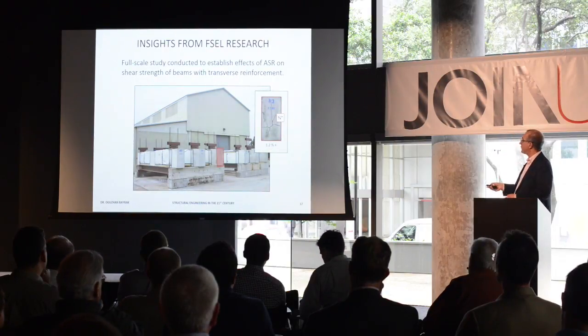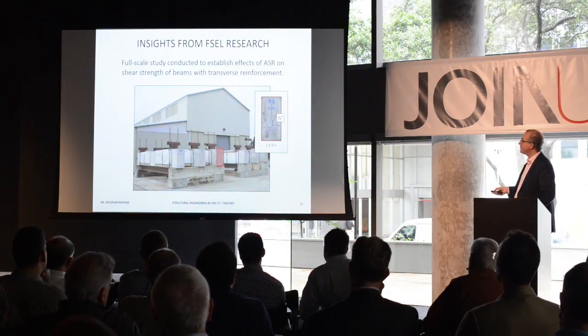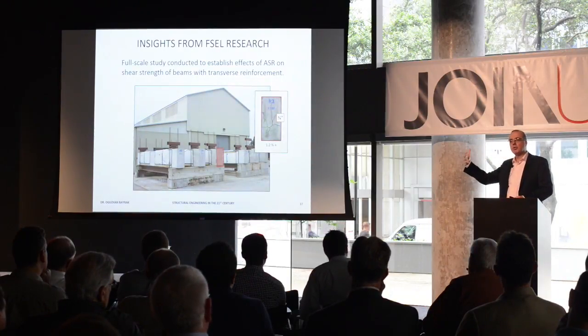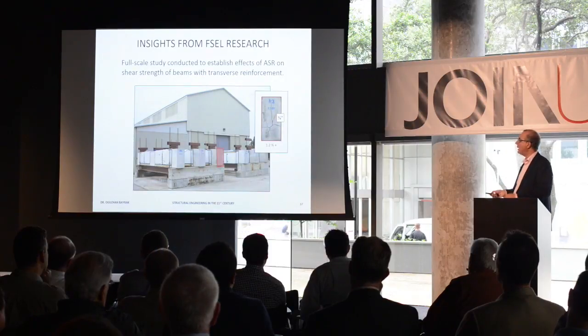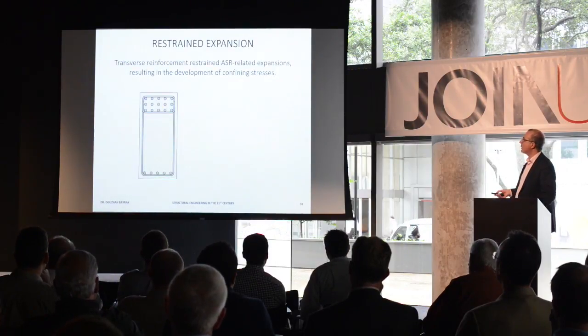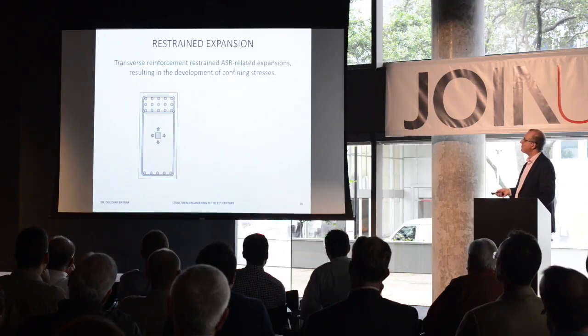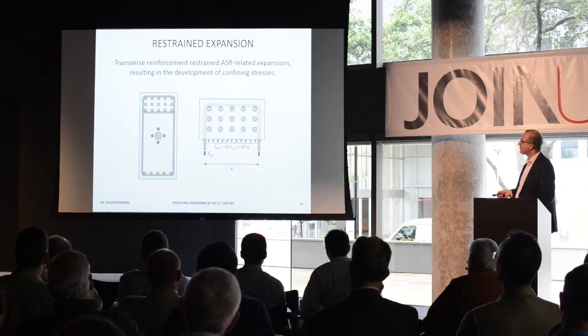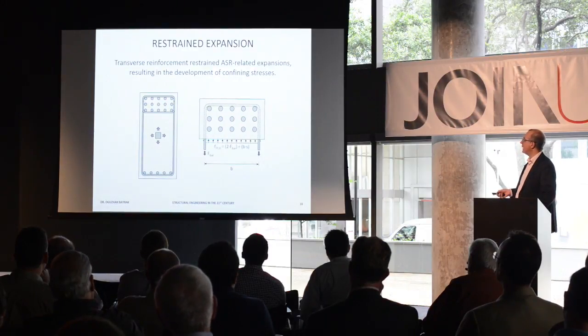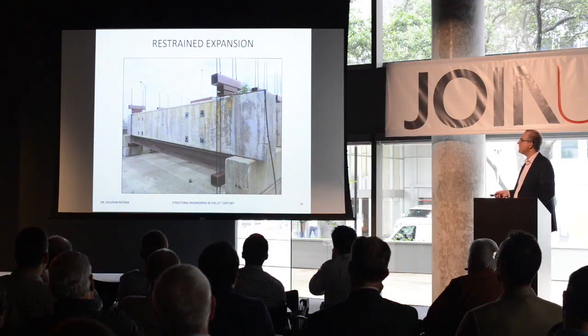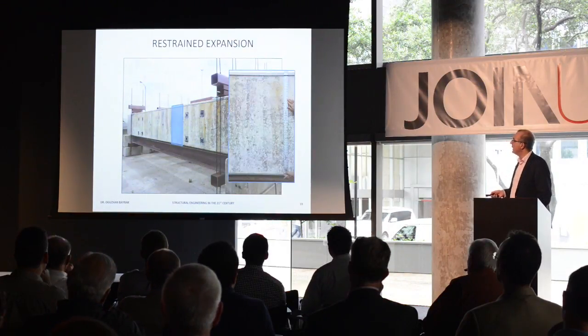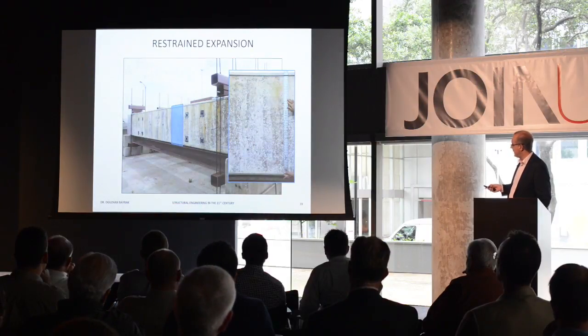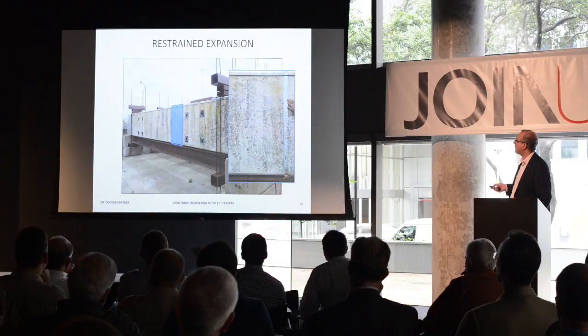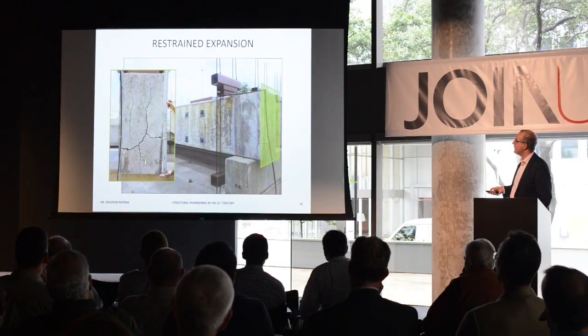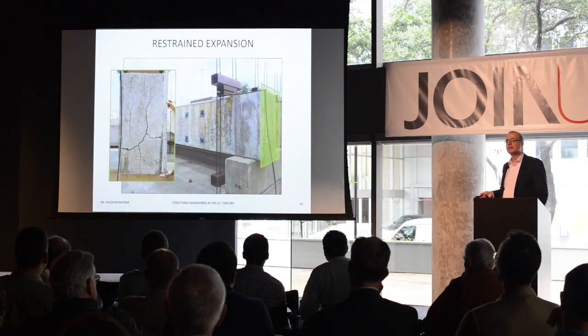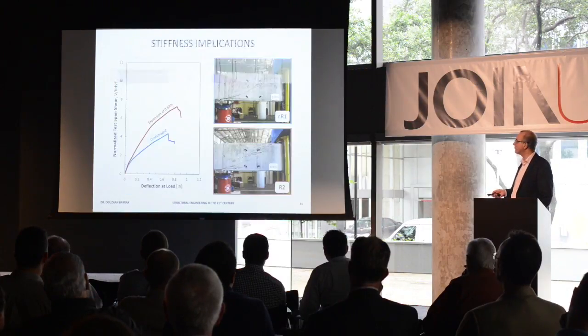The reason the cracks can be so large is in the end face of the beam, we don't have a rebar mat that's crossing those cracks, and the cracks are able to grow freely. As opposed to the side face of the beam, where the situation is a little different, we can take a look at the cross-section of that reinforced concrete beam, take a horizontal cut, and work on the mechanics and figure out the effects of confinement, but that's not the purpose of today's talk. Focusing on the side face, you can barely make that. We have micro cracks or hairline cracks scattered all over here, but you take a look at the end face of the beam, you can immediately see the role of the rebar mat that may be present in that beam.